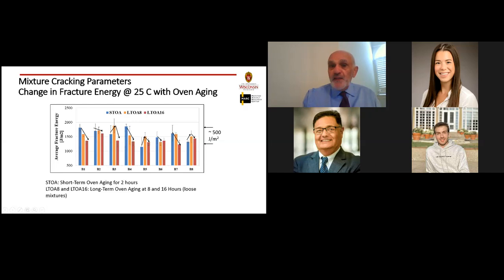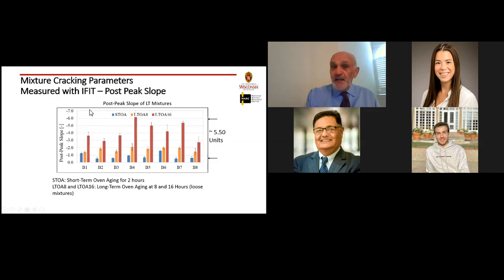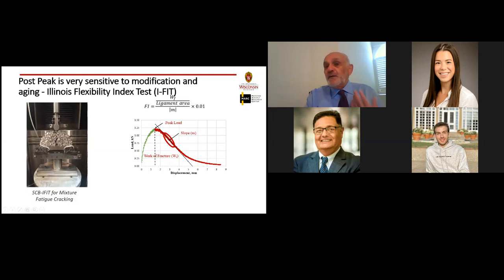And therefore, if anyone who is really specialized in testing looks at this, they would say, I'm not going to be able to differentiate between mixes by only using fracture energy. Certainly you cannot do that. You actually added the M slope, the post-peak slope. And now you can see very important differentiation between aging levels, as well as between different types of binders. In fact, the range is 200% of the average value. This is what we need to look at: a test that can differentiate between mixes and actually represent the material just before or after it is trying to fail. So this M value captured our attention to look at the binder and see, can we relate binder properties to this M value?